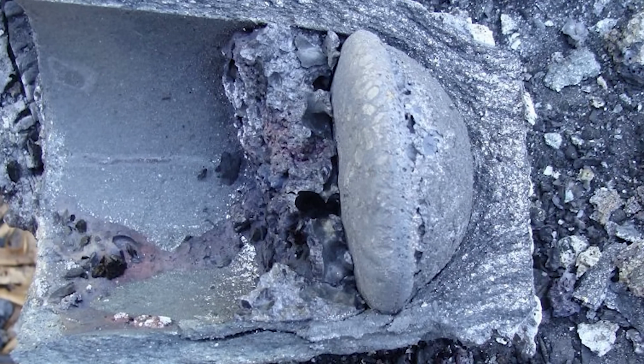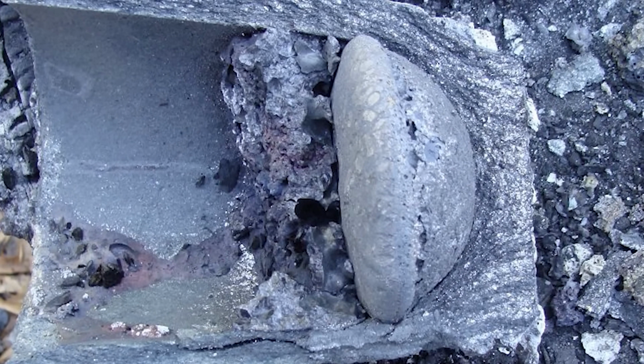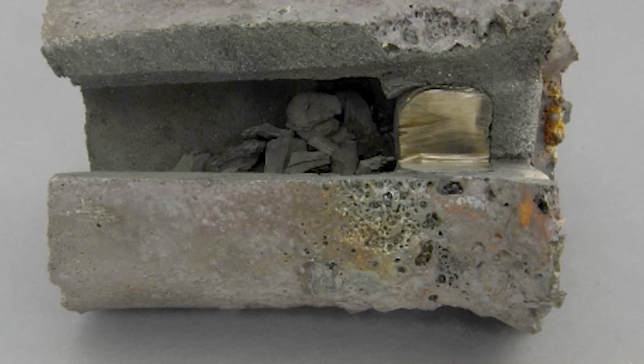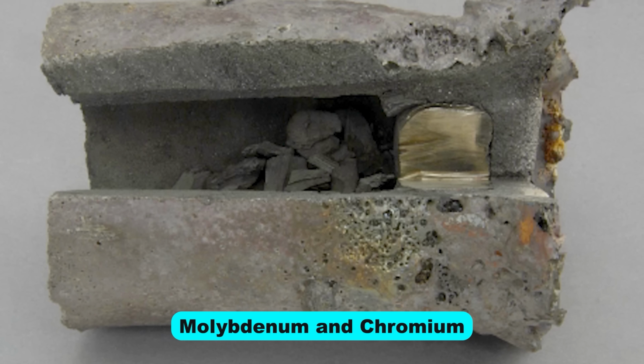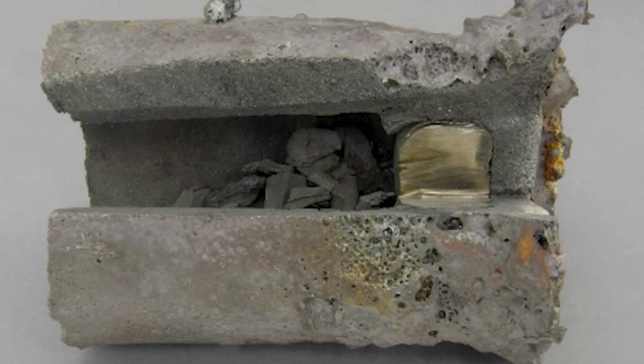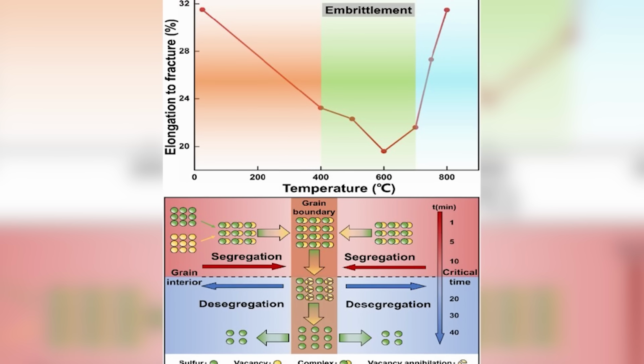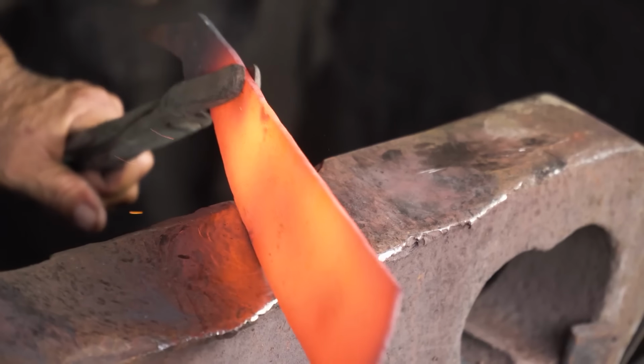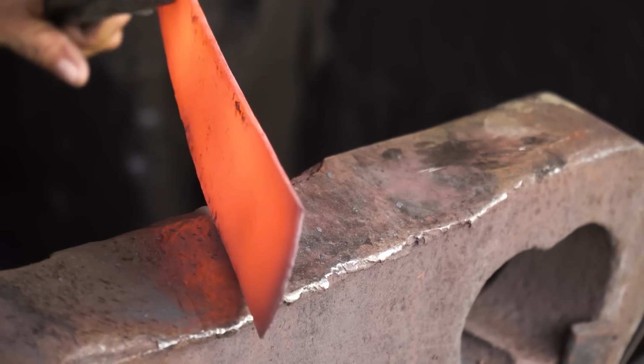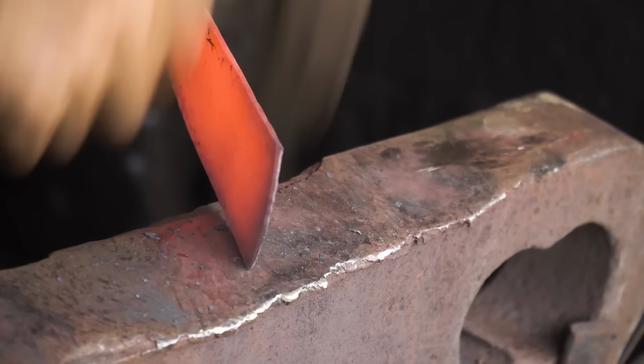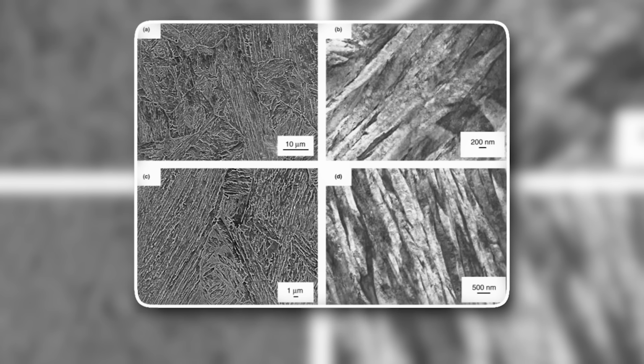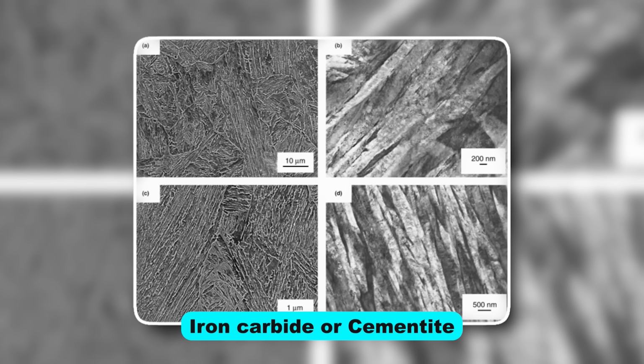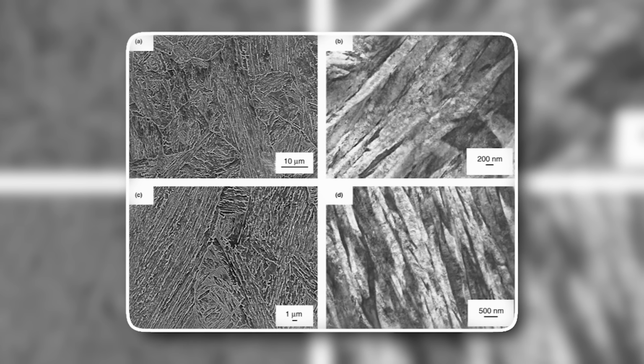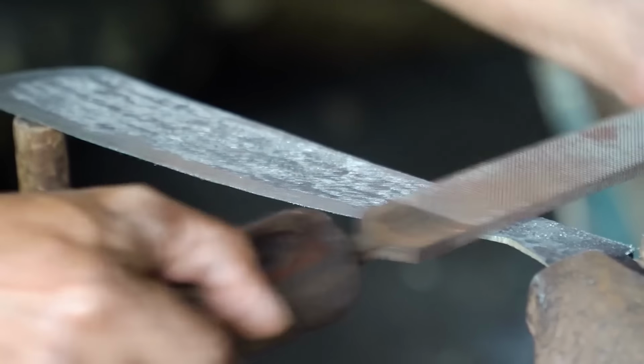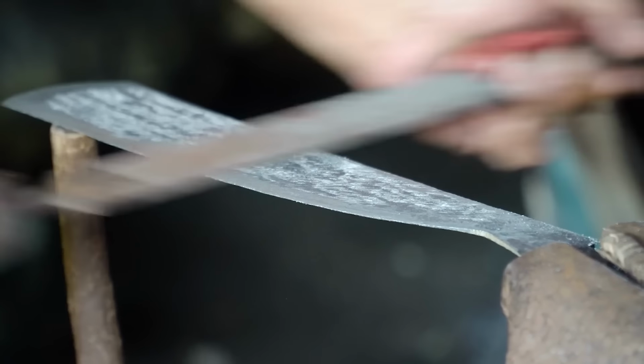Here's what it did. When the Wootz ingot cooled after smelting, the vanadium atoms, along with other trace elements like molybdenum and chromium, were pushed out of the solidifying iron crystals. They accumulated along the boundaries between crystal grains, forming thin sheets running through the steel. When the ingot was later heated and hammered into a blade, these impurity-rich zones acted as nucleation sites, places where an extremely hard compound called iron carbide or cementite clustered preferentially. The result was alternating bands of carbide-rich and carbide-poor steel running through the blade.